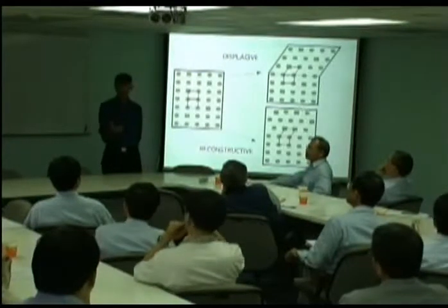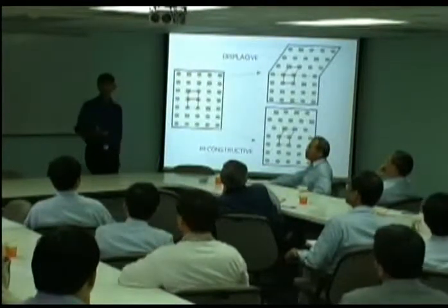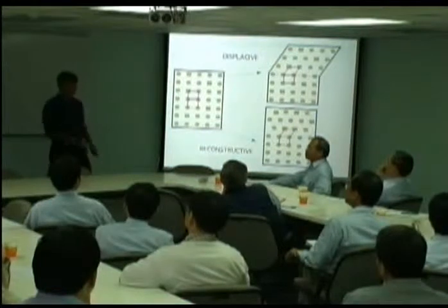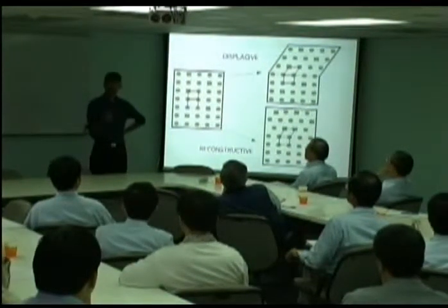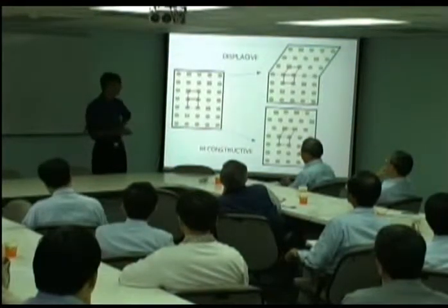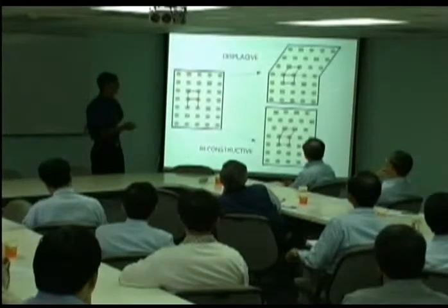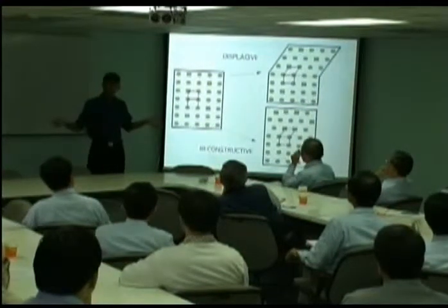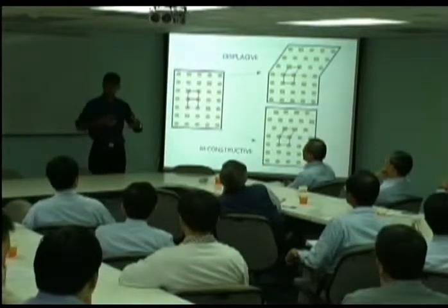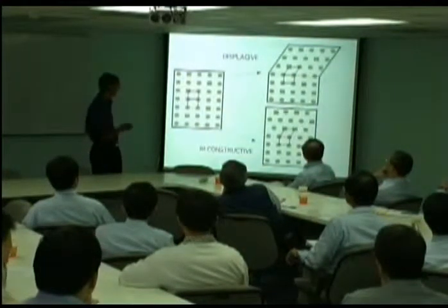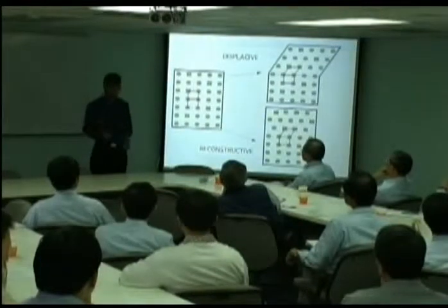Yeah, it's very, very small. It's about 10 to the minus 2 or 10 to the minus 3. The strain over here, the shear, is 0.26. Huge deformation. And remember that it's going to happen surrounded by a lot of material, so it's going to try and push against all that material. So there will be a huge strain energy. So these transformations are dominated by strain energy.